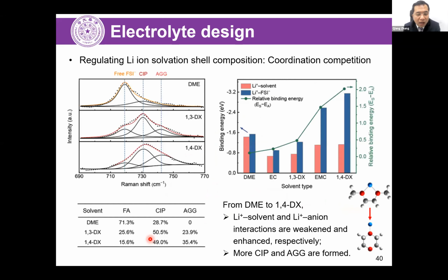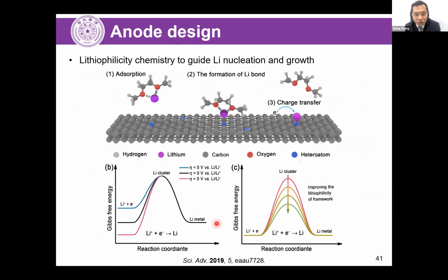And in this case, if we observe the states of lithium ion, it is found that the pairs and also the aggregates of lithium salts can be dominant with the introduction of dielectric solvents. The lithium ion is not dominantly in the unsolvated complex structure. The pairs or the aggregates are the dominant ones. And it is found that such electrolytes can give the cell fast charging properties, because the lithium pair moves more quickly than the lithium ion solvent complex in working electrolytes.